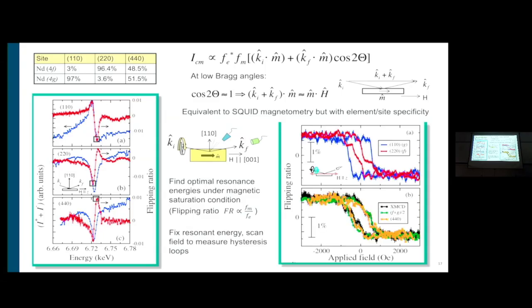So what we can do here now is say, okay, let's tune the energy to this particular resonance when the charge-magnetic interference is the strongest. And now let's reverse the magnetic field. And I can do a hysteresis loop that is only sensitive to neodymium and only sensitive to one or the other side. And these are the curves here. For the 110 Bragg peak and the 220 Bragg peak, I stay at this energy, I flip the direction of the magnetization, and you see that the hysteresis looks quite different.